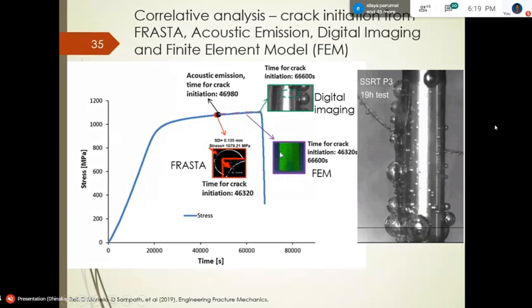And simultaneously we also videographed the entire test. What happened was the crack didn't appear until the very last point, at which the load fell off precipitously. As I told, here you can see the shiny specimen as fresh as it is. Then you can see the hydrogen bubbles generating on the surface. Not all hydrogen produced on the surface gets into the material. Only a small fraction of it gets in. But still, that's virulent enough to cause the damage.